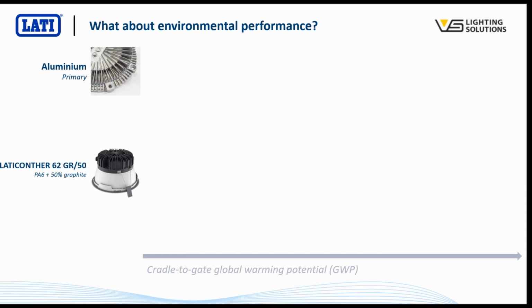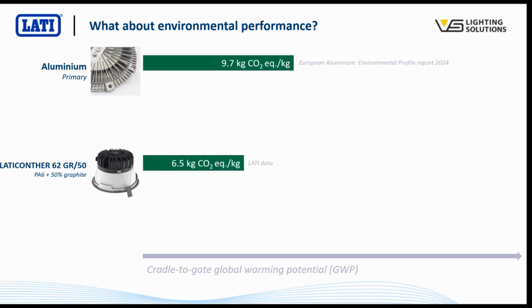So if we look at the global warming potential for aluminium to begin with, it's around 9.7 kilograms of CO2 per kilogram of material, and this is data from the European Aluminium Association's most recent environmental profile report, and this is taking into account the aluminium that's consumed in Europe. So that aluminium might be sourced from all around the globe, but it's intended to represent the product mix that's actually used in Europe. And if we look at the plastics, and this is LATI data, then we see that it's slightly better at 6.5 kilos of CO2 per kilo of material.